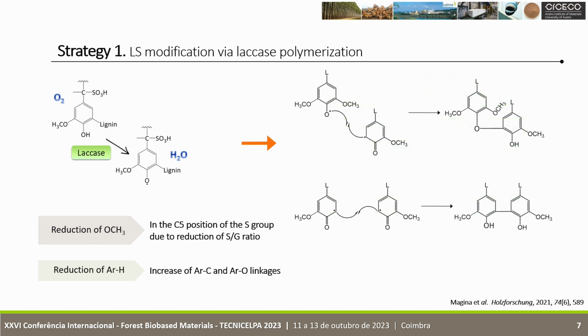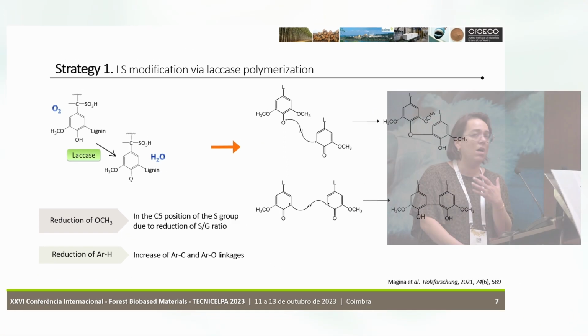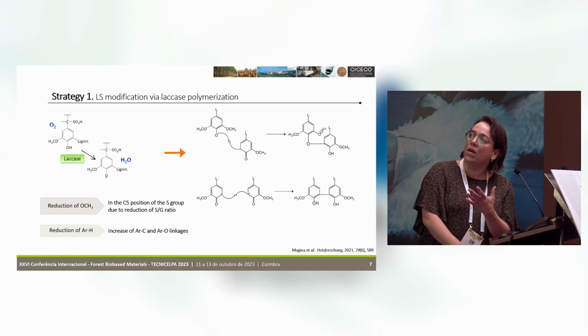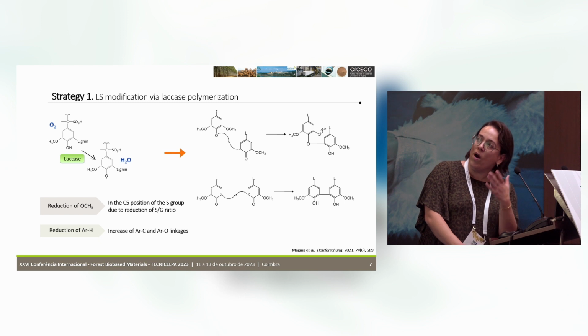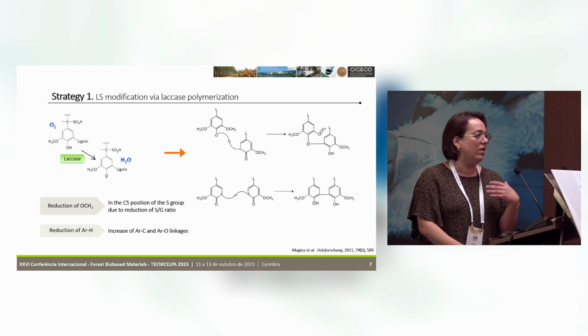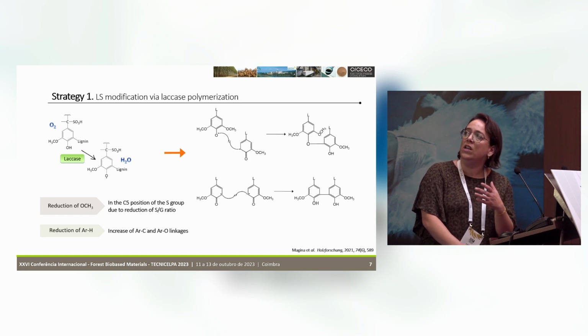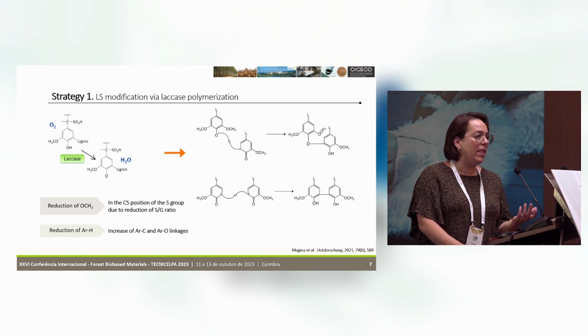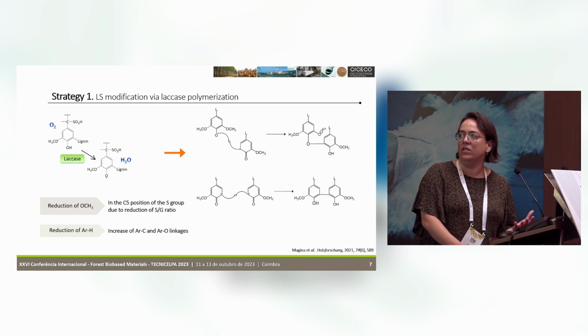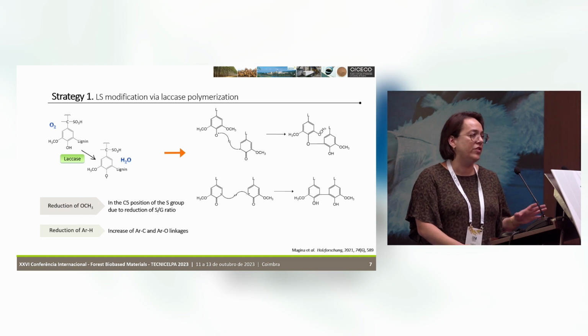Probably because the polymerization was via radical coupling by two possible mechanisms: the radical coupling of one electron-oxidized lignin with another one, leading to the formation of aryl ether structures and biphenyl structures. So this was the first approach.